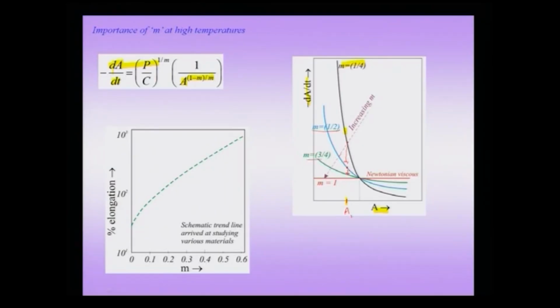This implies, if I am going to compare different materials with different strain rate sensitivities, it is better for me to have a higher strain rate sensitivity, because in that case the reduction in area per unit time, that means dA by dt, would be smaller. That means my deformation is not going to be localized, and therefore the deformation is going to spread across the sample, and therefore I can get higher elongations.